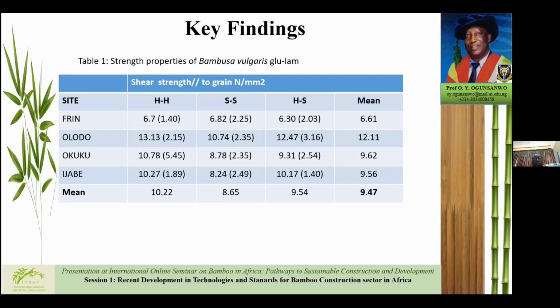Now, in terms of shear strength along the glue line, this is an attempt to pull bamboo apart along the glue line. We could see from this table that HH, that is back-to-back bamboo lamination, had 10 Newton per mm square. For SS, which is the lowest, 8.65, and then you have 9.54 for H and S. The expectation in this result is that we were expecting that SS should have the highest, because according to what we found out in